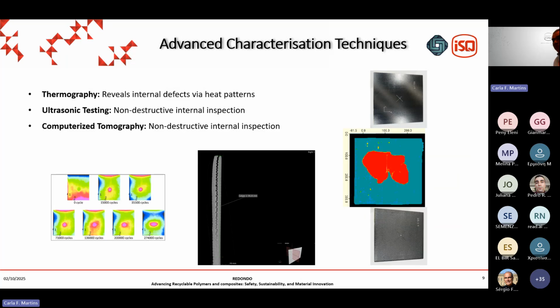Other techniques that have been very interesting for this testing, which are not so much applied to the test itself, but to the analysis of the test results, are thermography, ultrasonics, and computerized tomography. Probably thermography can be used as well, theoretically, for the test itself, to monitor the test. Here we have the evolution of a defect in a specimen during a fatigue test, and the evolution of that defect was identified by thermography. It must be used with some care, particularly in composites, because it involves elevated temperatures, well, between inverted commas, but they could affect the material, because composites are not very famous for their heat resistance.